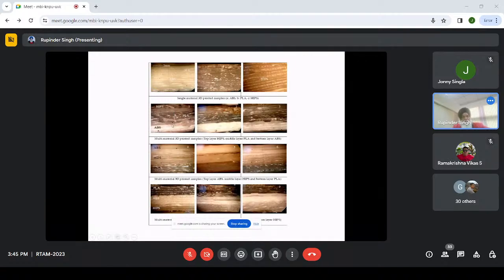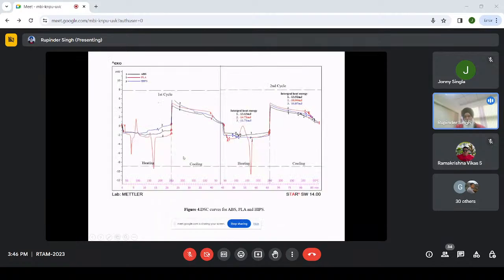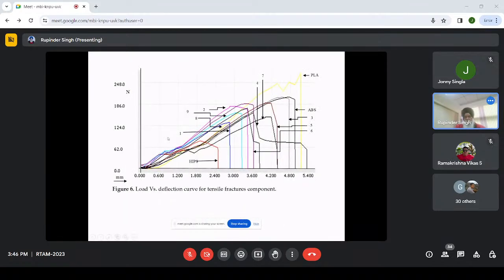Then if I see the experiment number 1, the ABS was put first, followed by PLA, followed by HIPS. So once I put the PLA over the ABS, what happens? The side globule formation was observed. That means once I print the ABS and then I print the PLA, the material will have a side flow, right? Now, if you see the experiment number 4, once the PLA was down, then HIPS and then ABS, there was no side flow. Now, if I just compare it with this graph, in case 1, this was the area under the curve, and in case 4, this was the area under the curve, right?